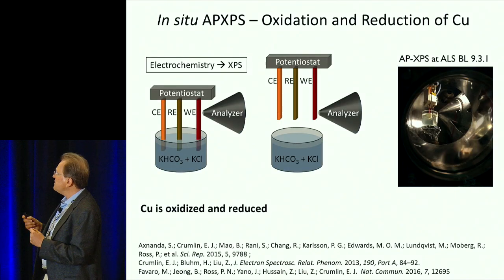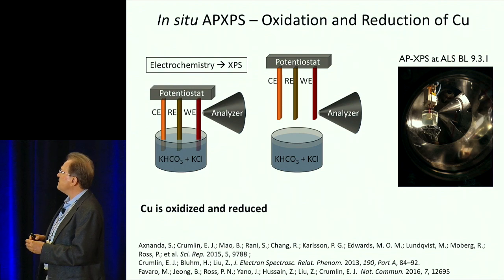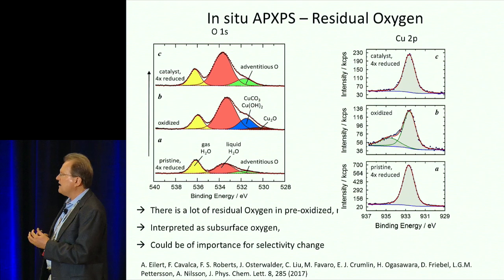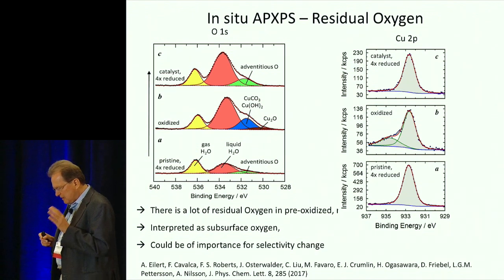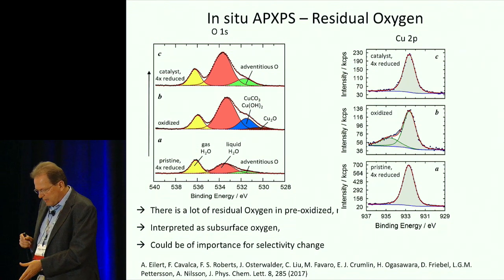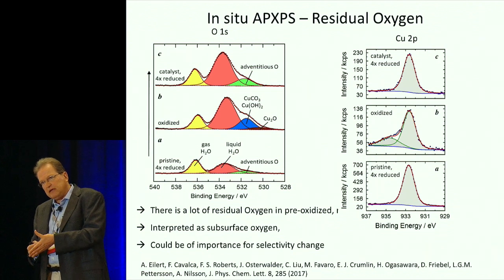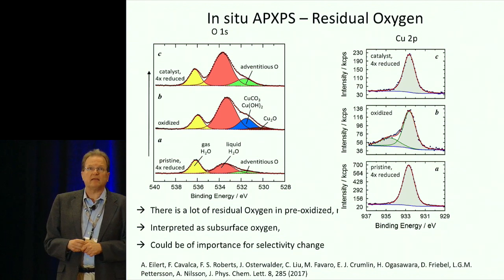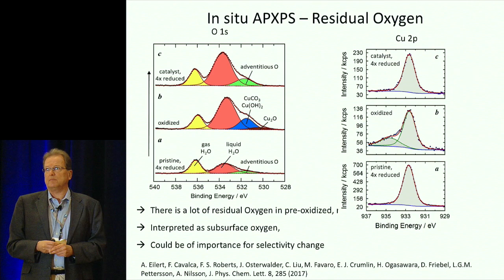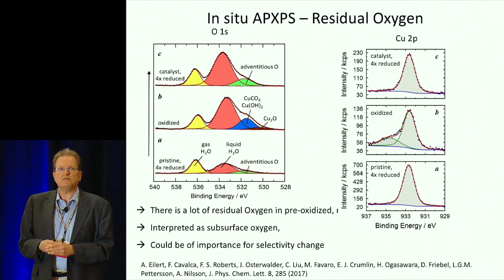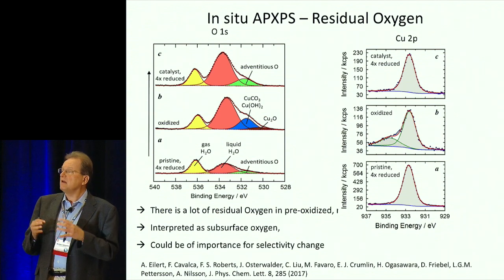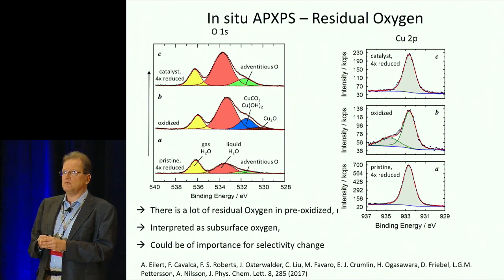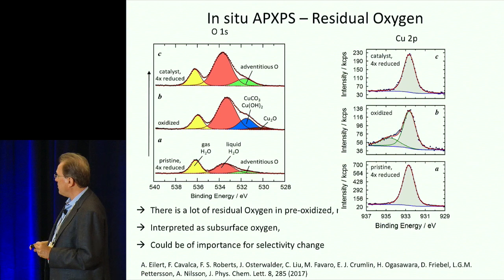And what we've done is an in situ XPS measurement under reaction conditions. I'll finalize by saying that as we run the reaction electrochemically and take out the sample, still wet, we're seeing that there is oxygen left in the system. This is now an interesting aspect to understand, why that is happening, and whether this is actually very important for the chemistry. But it's only one of these hypotheses.